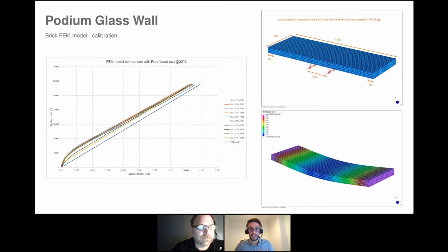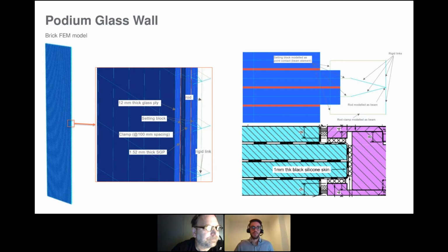And what we saw to validate the good level of, let's say, our brick model was compare these two results, and we can see in the diagram that basically the predicted behavior from the finite element model, that is the straight line in blue, is very, very consistent with the results expected and extrapolated by the test results. So what we had to do was to run analysis of single panels to understand the behavior of the panel and the distribution of the stress across the plies, as it was requested by the approving authority. So we had to build this model.